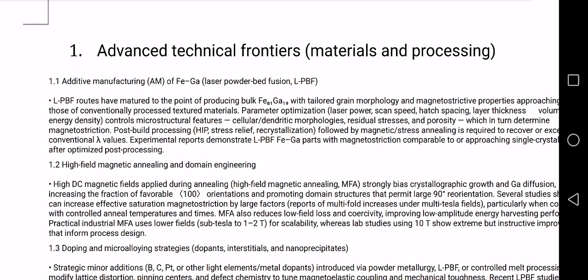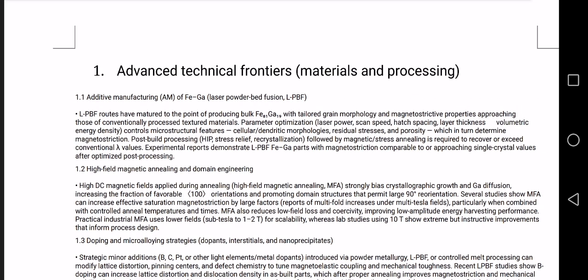Additive manufacturing, LPBF of FeGa. Let us start with additive manufacturing. Laser powder bed fusion uses a laser to melt FeGa powder layer by layer. It enables complex 3D geometries. Recent progress shows LPBF can now produce Fe81Ga19 with controlled grain structure and strong magnetostriction.